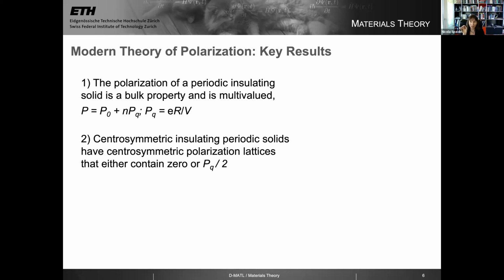So polarization is not a single number, it's an array, a lattice of numbers, and it's given by some P0 plus n times the polarization quantum, where the polarization quantum is the charge times the lattice vector divided by the volume. Centrosymmetric solids, those that are non-polar, have centrosymmetric polarization lattices. And if you want an array of numbers to be centrosymmetric, to be equal at plus or minus, there are only two ways you can do that. You can do that if they contain 0, or you can do it if they contain half a quantum. And so these, I'd say, are two really key results of the modern theory of polarization.